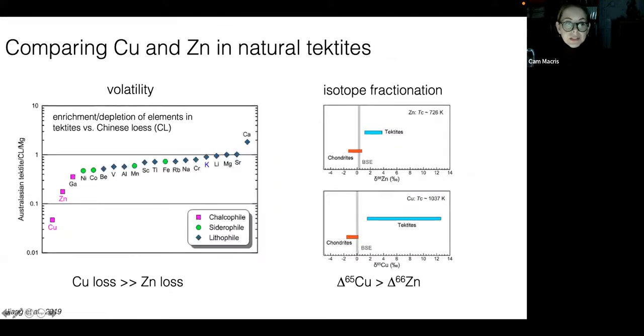So on the left here, we're still looking at the volatility of copper and zinc, but now in natural samples. This is a plot of the relative enrichment and depletion of elements in tektites versus Chinese loess, which some think is the protolith of tektites. And what we see is that copper is much more depleted and therefore is more volatile than zinc. Over here on the right are the plots I showed earlier of copper and zinc isotope fractionation relative to bulk silicate earth. This time zinc is on top and copper is on the bottom. This also agrees with our experiments in that copper is more fractionated than zinc in these tektites.